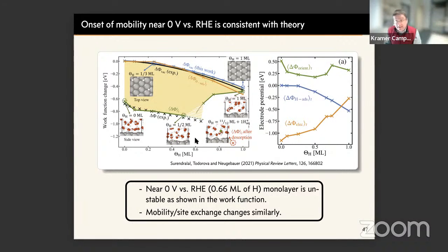The specific thing that they would argue is added in this contribution is that they have a scheme to really reference their electrode with high precision. And if you do that, what you find is that as you approach about 0.6 monolayers of hydrogen, so this is the surface coverage of hydrogen at 0 volts RHE, the surface becomes very unstable, right? The hydrogen starts to desorb, and the system wants to jump back to a similar work function describing the vacuum adsorbed case at high coverages.